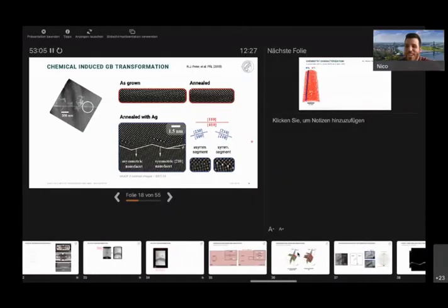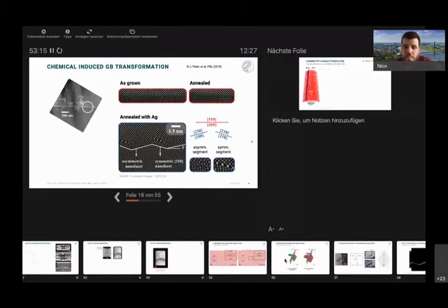No, unfortunately, we don't have that simulation. So the problem is, you can do MD simulations, and molecular dynamic simulations give you a very good sense of the structure. So small movements of atoms, for example, can be nicely simulated. If segregation comes into play, that's on a very different time scale. So you need much longer simulation runs to actually have silver diffuse. And this is what is needed in the simulations.